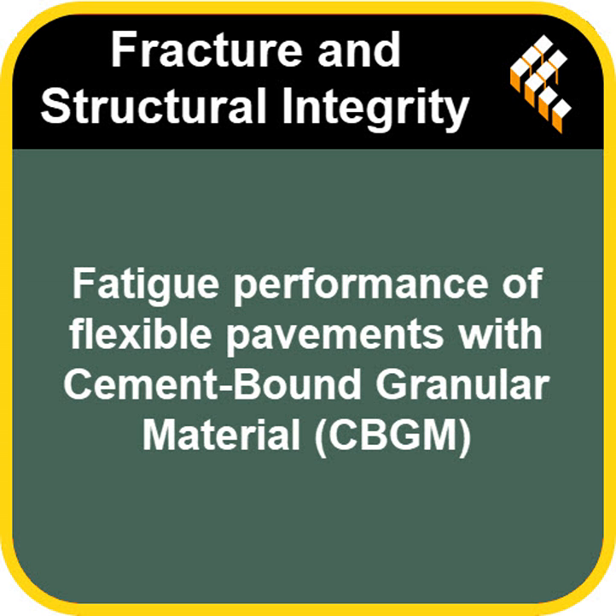That sounds critical. The study mentions Judice's work, showing how this modulus changes dramatically depending on the CBGM strength, the type of aggregate, and crucially, whether it's in that strong, uncracked state or the weaker cracked state. Like the example you gave, it could start off almost like steel, stiffness-wise. That's right, incredibly high, maybe 4.5 gigapascals or GPa. But then, in a small block cracked state, it could plummet to something more like dense rubber, like 160 to 350 megapascals, MPa. Exactly. That's a huge difference in stiffness, orders of magnitude, potentially.